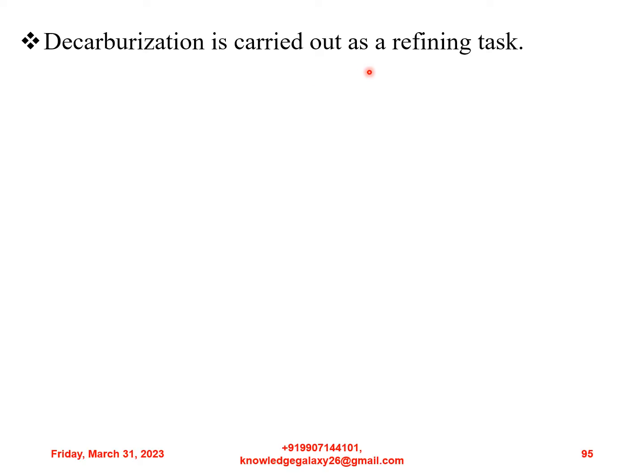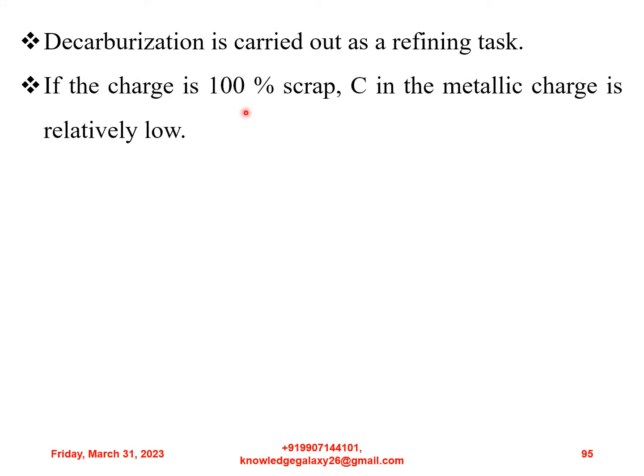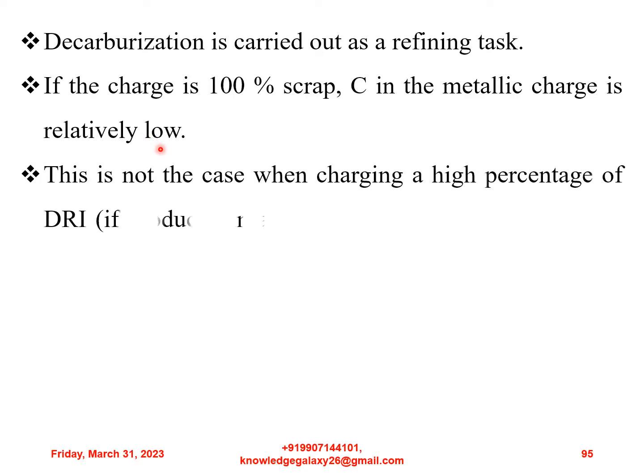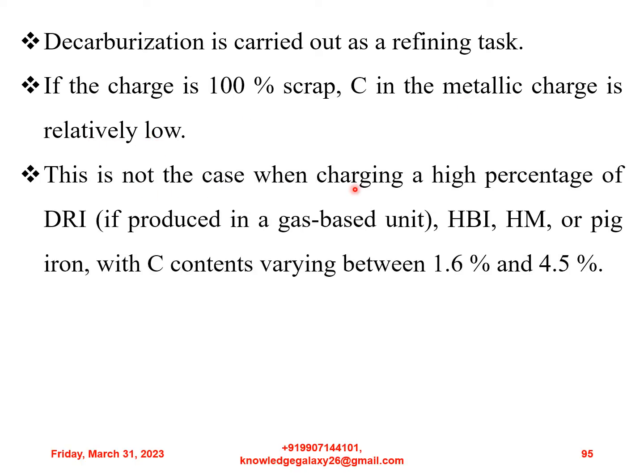Decarburization is carried out as a refining task. If the charge is 100% scrap, carbon in the metallic charge is relatively low. This is not the case when charging a high percentage of DRI, that is, if produced in a gas-based unit, HBI, hot metal or pig iron with carbon contents varying between 1.6 to 4.5%.